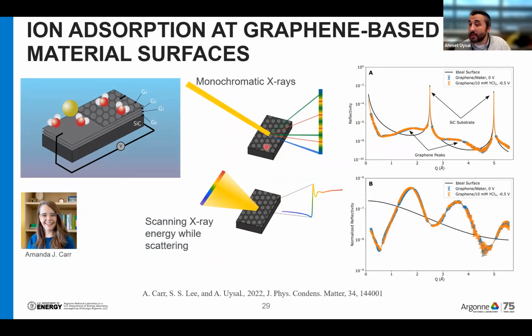And one is X-ray reflectivity, or since we have a crystalline substrate, we can do crystal truncation rod measurements, high-resolution X-ray reflectivity. Also, we can tune the X-ray energy around the yttrium absorption edge, and we can do resonant anomalous X-ray reflectivity to determine the ion position directly. This is a very great advantage that we have at APS.